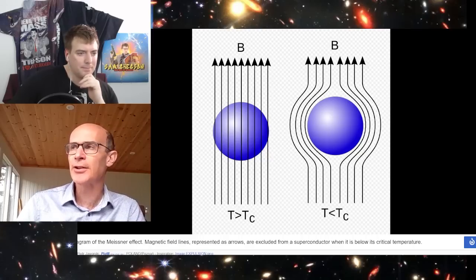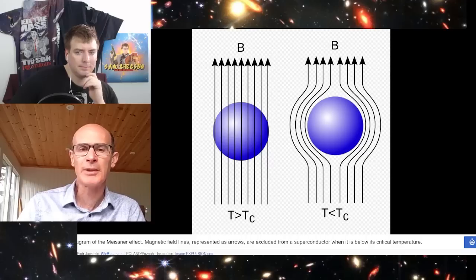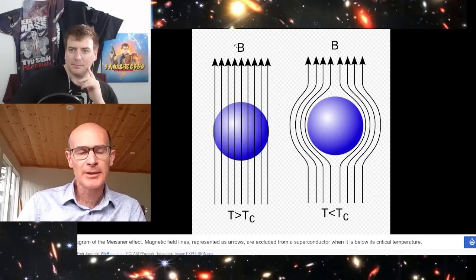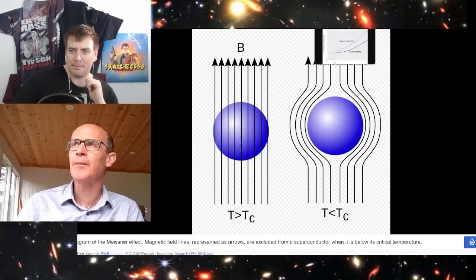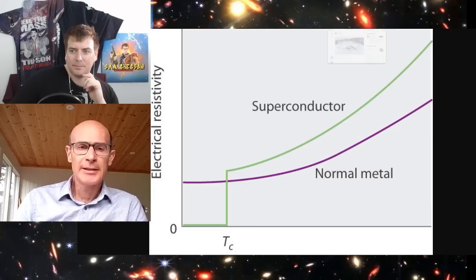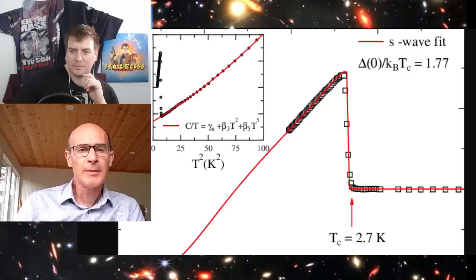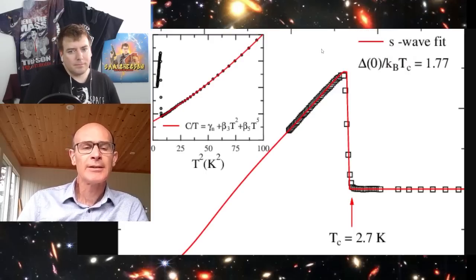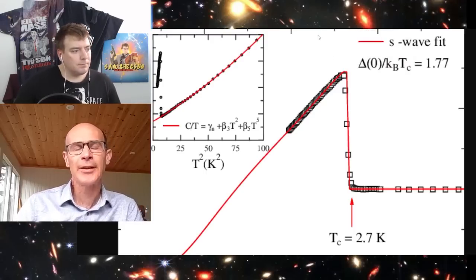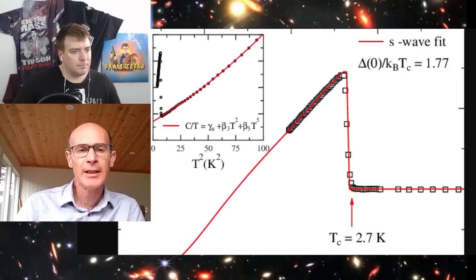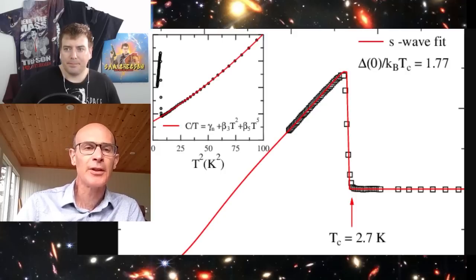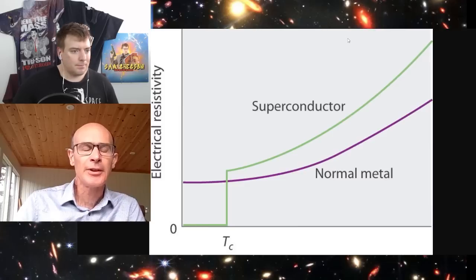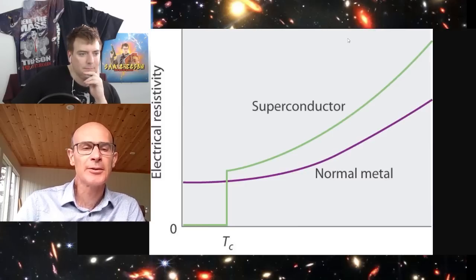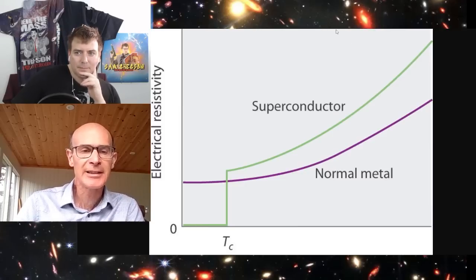So you have to go through the transition and show that it goes from being a metal to becoming a superconductor on cooling, and there should be a heat capacity change at that transition. So measuring the heat capacity would be a standard test for a superconductor. And the other test you can do, although I mentioned the technical difficulties, is to measure the resistance, which should drop to zero quite suddenly at the transition temperature, and that just requires skill to measure accurately. The magnetic test is easier because you don't have to attach anything to your sample.